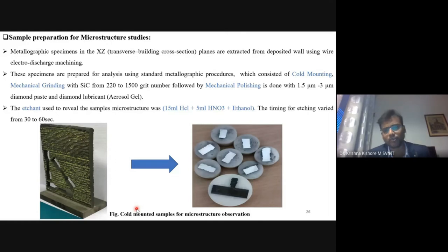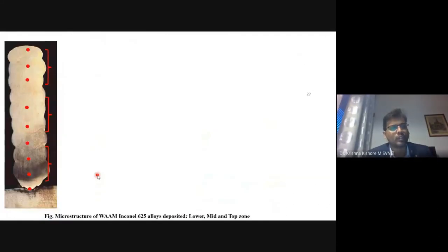And for the microstructures, these samples are generally etched with a combination of 15 ml HCl, 5 ml HNO3, and ethanol. And these samples are extracted in the entire layers. We have extracted at the middle, top and bottom. And this microstructure has been thoroughly studied. So this is our strategy.